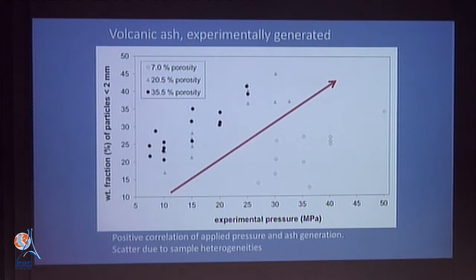We looked at various properties of the ash as a function of temperature and pressure, and you can see one example here of experimental pressure versus the weight fraction of the fine particles in the ash, and you can see a correlation between the two. More pressure, more energy, more fragmentation, more surface, finer ash. Okay? And we have the advantage that we can measure the specific surface. The devices are routine in material science. We can measure the grain size, which allows us to independently calculate the specific surface based upon particle shape approximations. You can do a lot of things with these materials.